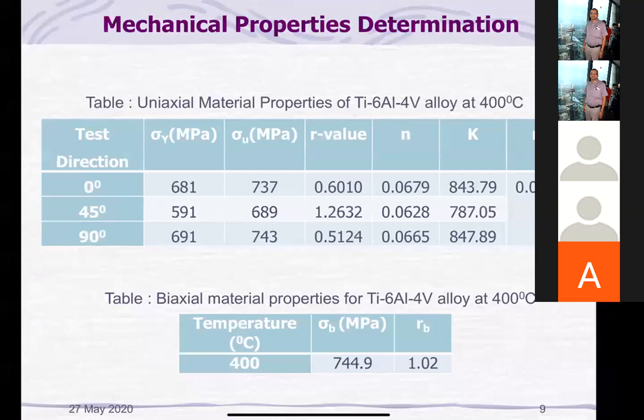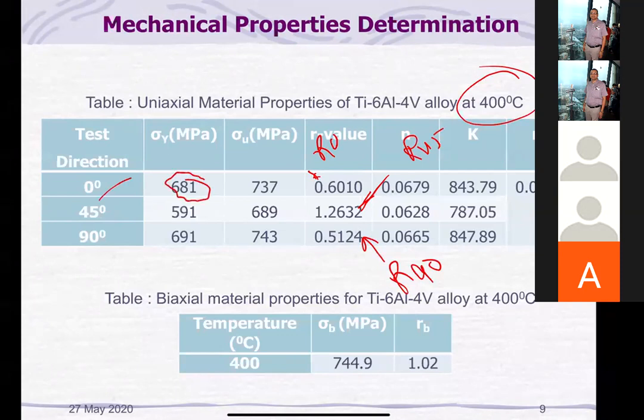We are discussing titanium. At 400 degrees centigrade, these are the properties. This is called R0, this is called R45, and this is called R90. We can see here that there is a lot of variability in the material. Even the yield strength at 0 degree orientation to the rolling direction has almost a difference of 100 MPa in the 45 degree direction, and again back to square one at 90 degree. So huge variability in the yield strength and ultimate tensile strength. We can see this by the Lankford parameters R0, R45, and R90. But in N value, there is not much significant variation.